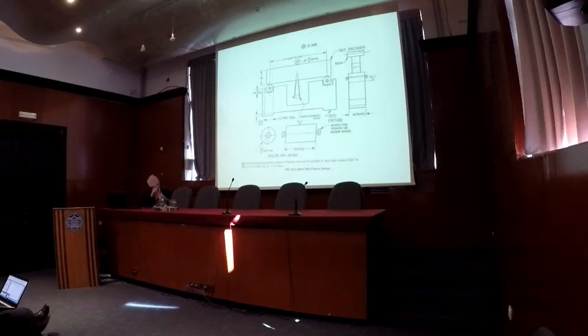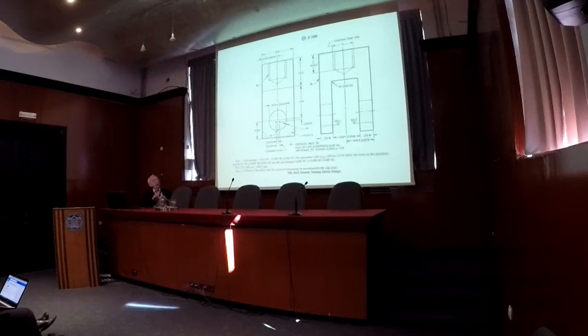Here is a bend specimen in a fixture. You can see it's set in the fixture, and here is a displacement gauge that when you load that, you have to measure both load and displacement, so for the K1C test, you need a gauge like that.